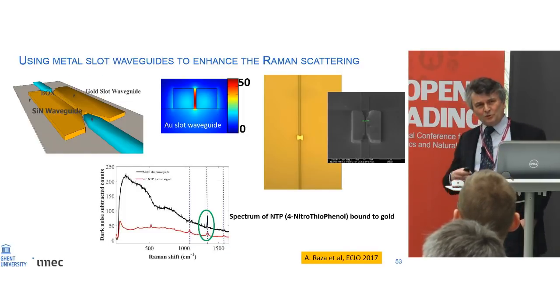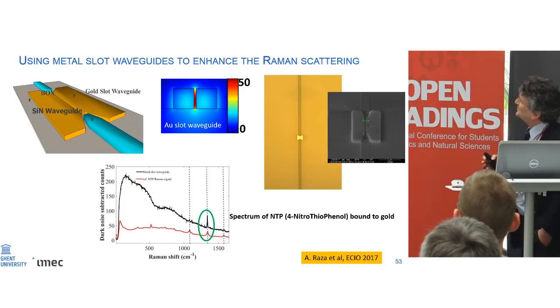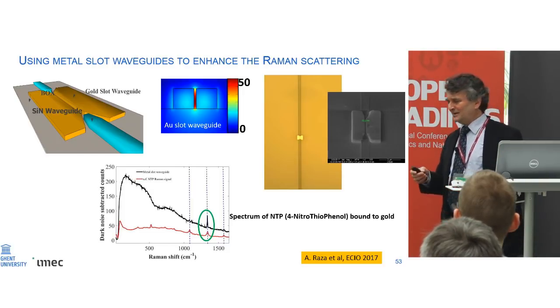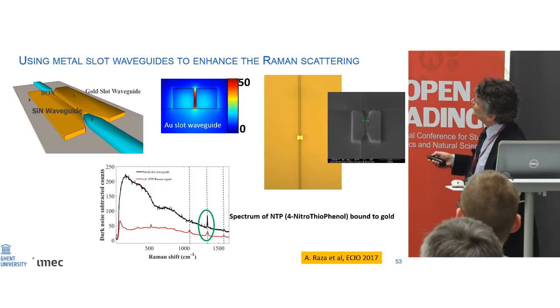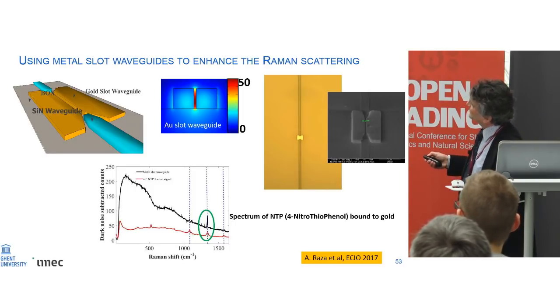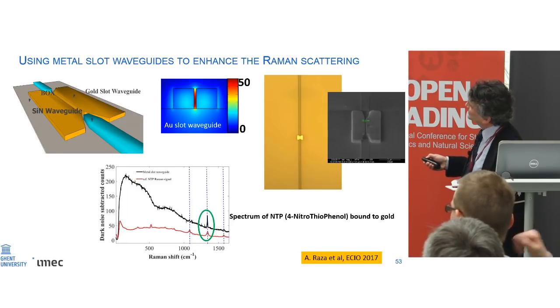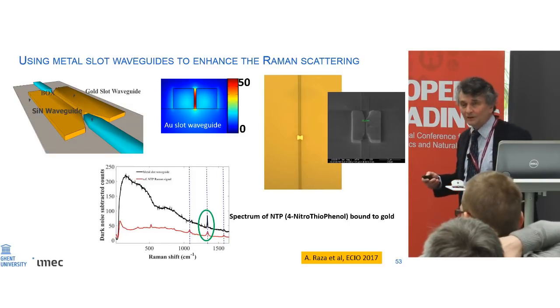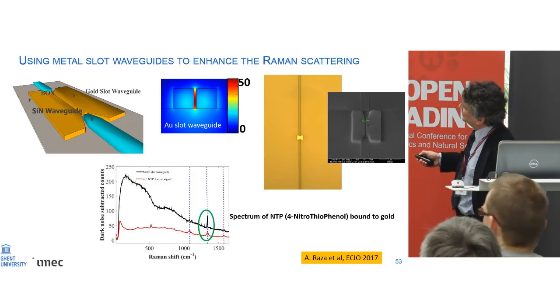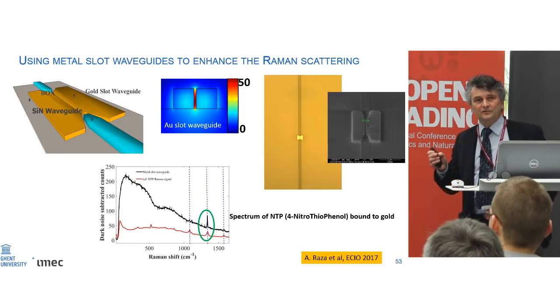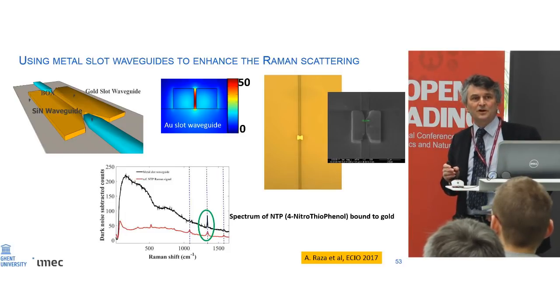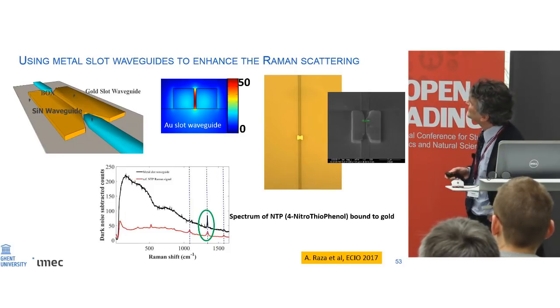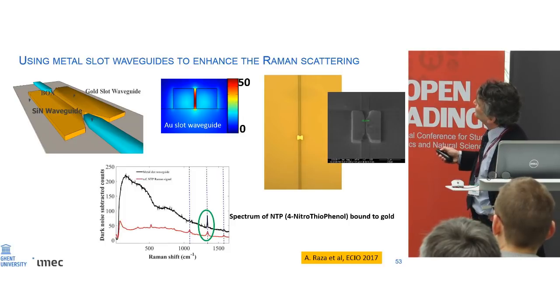Okay, we are now taking all of this further, and actually we are going a little bit away from the normal dielectric waveguide, but we combine the dielectric waveguide now with a plasmonic waveguide. What you see here is, this is gold, and you see here a metal, it's a slotted metal waveguide. And again, the analyte is sitting in this slot, and the slot in this case for a plasmonic slot is actually very narrow. It's down to perhaps 20 to 30 nanometers. Gives you a huge electric field enhancement in that slot.